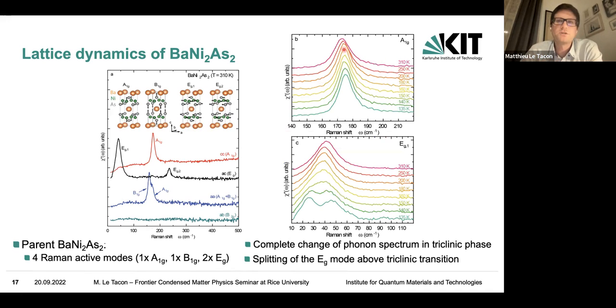And then we got interested in what happens above the triclinic transition. So we first look at the A1G phonon, and you see that this mode sharpens and hardens as we cool down to 135K, something like that, just above the triclinic transition. And that's exactly what you expect for a well-behaved phonon. Now, when we look at the EG mode, what we see is that it's broad, and first you see that it softens upon cooling, which is normally not supposed to happen because the lattice gets stiffer and the phonons tend to harden. And then clearly it broadens and it splits.